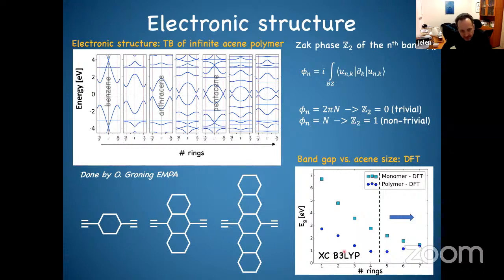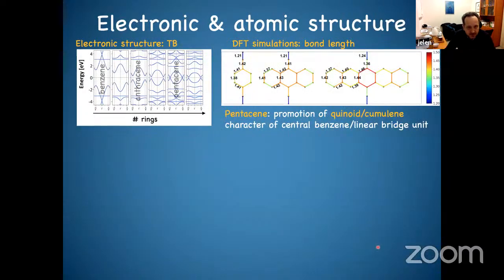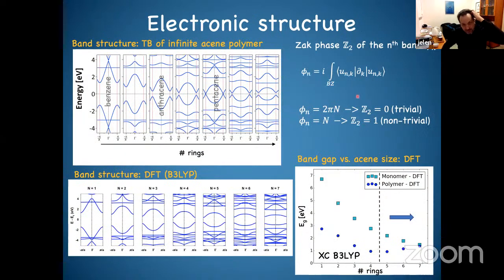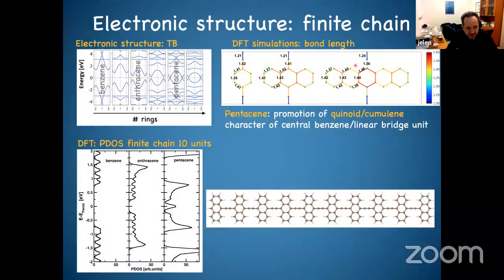And this is done with the exchange correlation functional B3LYP. Of course, the band gap will change accordingly. But you see again here, there would be some transition. One other thing is, if you really want to prove that you are in a topologically trivial or non-trivial phase, you want to calculate the so-called Zak phase, this Berry phase across the Brillouin zone. And again, we see that there is a change in the Zak phase.